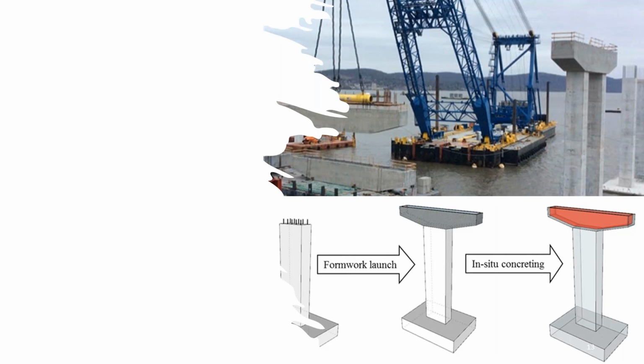Now, there are many advantages of doing that. In fact, people have done this. On the upper right-hand side, there's a bridge where the cap beam is actually cast-in-place normal strength concrete. It's a formwork that is cast, they bring it to the site, they put a steel cage inside, fill it with regular concrete, and then connect the elements together. Now, in our case, we are using a UHPC shell, and we are printing it. On the bottom right-hand side, you will see the concept: you print these different elements, bring them, it can be cast in place, but we are doing 3D printing. You connect them. We have done lots of work in the connection area, and I will show you some of the results. Then you put in the steel cage and fill it with the concrete.